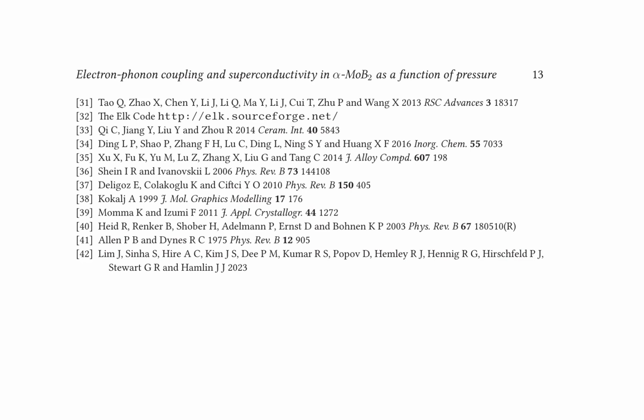Employing the ELK code, a full-potential linearized augmented plane wave method with local orbitals, FP-LAPW plus lo, is applied to calculate the electronic band structure and density of states. This reveals that alpha MoB2 has a complex band structure with multiple bands crossing the Fermi level, indicating a multi-band superconductor. Phonon dispersion calculations show that alpha MoB2 exhibits several phonon modes, some of which are soft and contribute significantly to the electron-phonon coupling. The paper highlights the importance of these soft modes in enhancing the material's superconducting transition temperature.